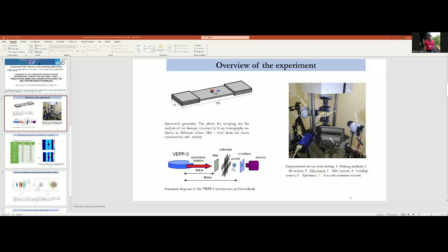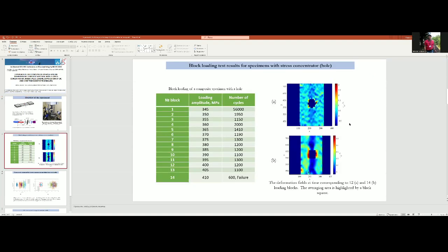Okay, next slide. Our fatigue test used a stepwise block loading protocol. We progressively increased the load from a non-destructive level to failure. We simultaneously used the DIC for strain field analysis and recorded acoustic emission. Each loading block was designed to provide stable and sufficient acoustic data for analysis, with a particularly long initial block to establish a baseline for damage.